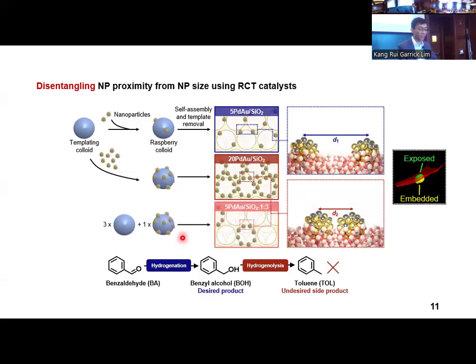Now, to further decouple the metal loading from the interparticle distance, the highly modular RCT method allows for the mixing of nanoparticle decorated raspberry colloids with nanoparticle-free templating colloids in a pre-calculated ratio. For example, by mixing raspberry colloids that would result in a 20% catalyst with nanoparticle-free templating colloids in a 1:3 ratio, we obtain a final 5% catalyst, but with an interparticle distance that resembles the 20% catalyst instead. This way, we can compare catalysts at the same 5% metal loading, but with different interparticle distances.